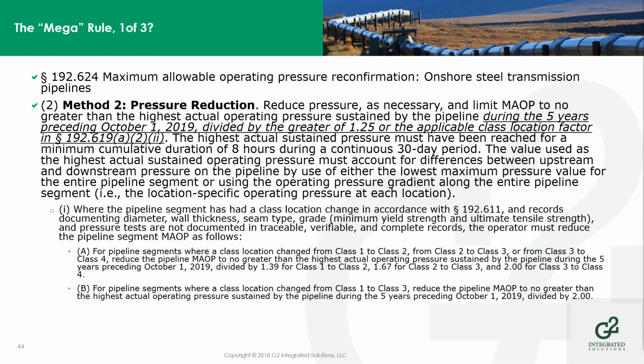So the highest actual sustained pressure has to have been reached for a minimum cumulative duration of 8 hours during a continuous 30-day period. The value used as the actual highest sustained pressure must account for differences between upstream and downstream pressures. So it's not just a matter of picking a high point on the chart or on the SCADA data or on the pressure record. It has to be an 8-hour period of continuous operation in a 30-day period. And then it has to meet these other accountabilities for upstream and downstream pressures in the pipeline for variances that are going to occur.